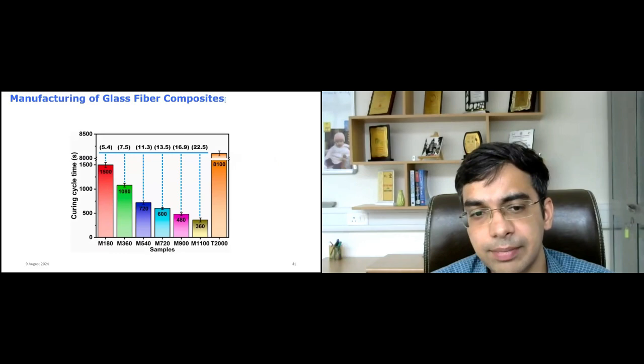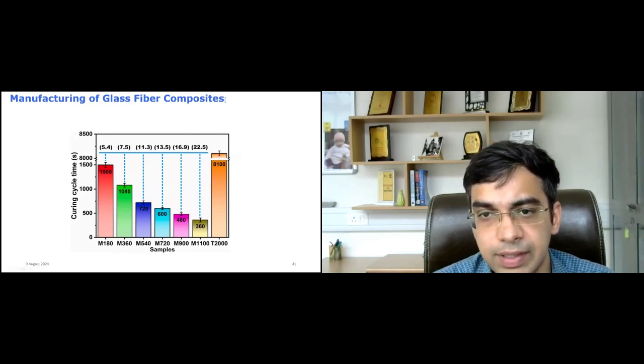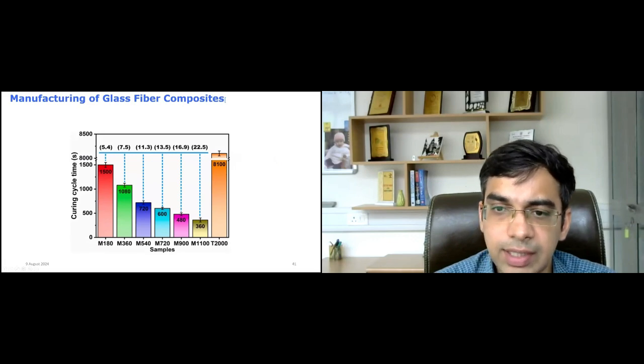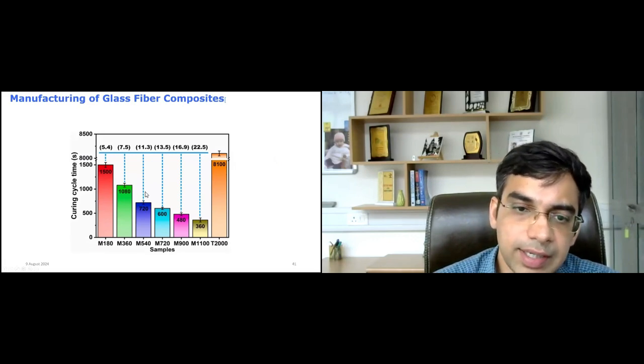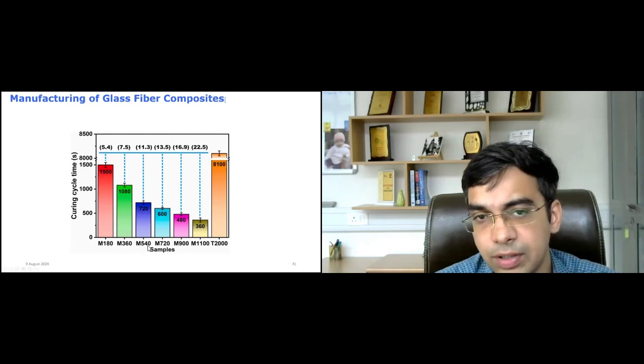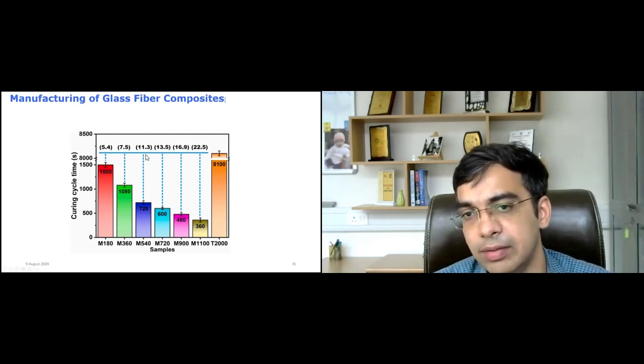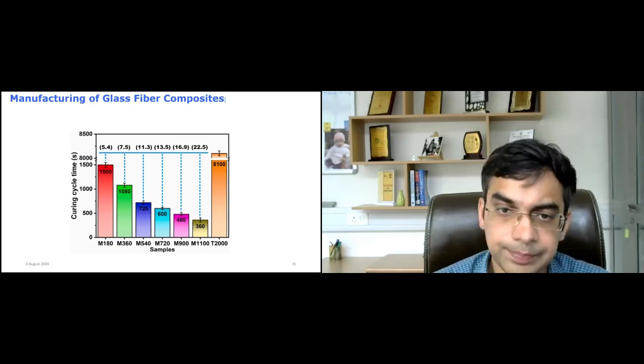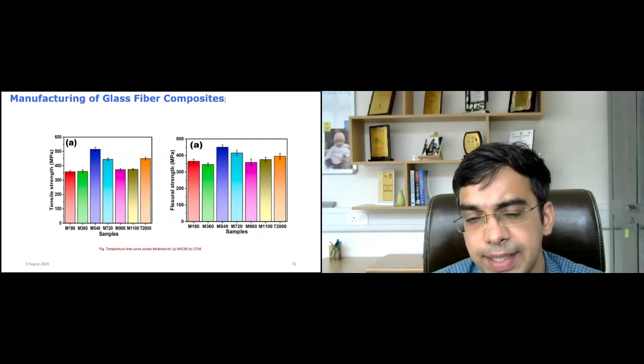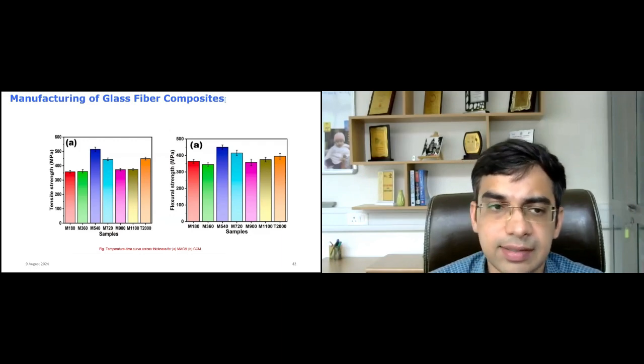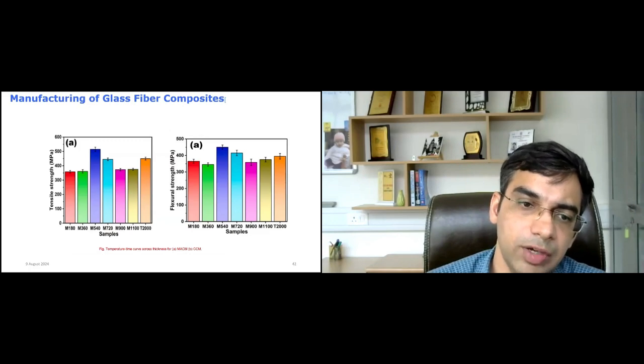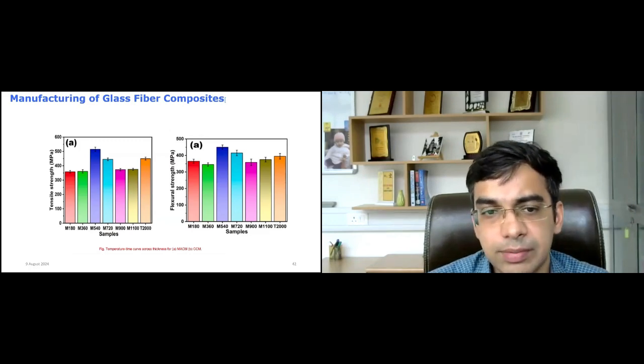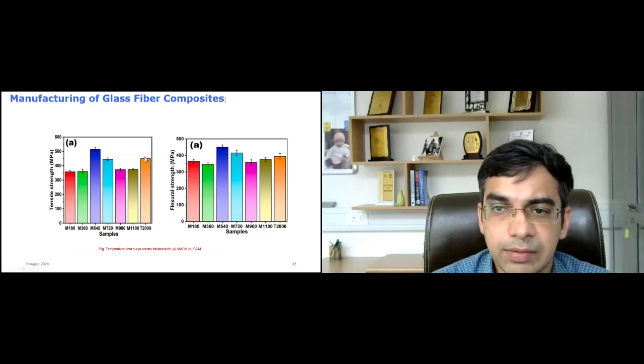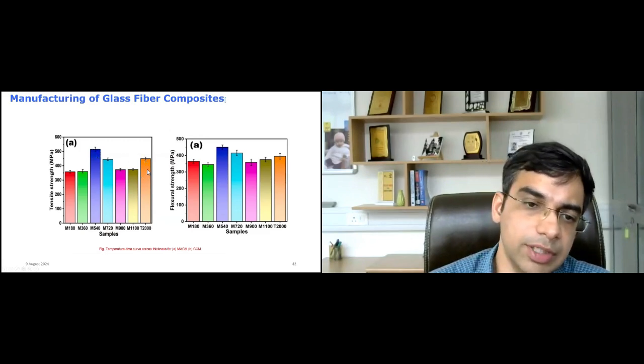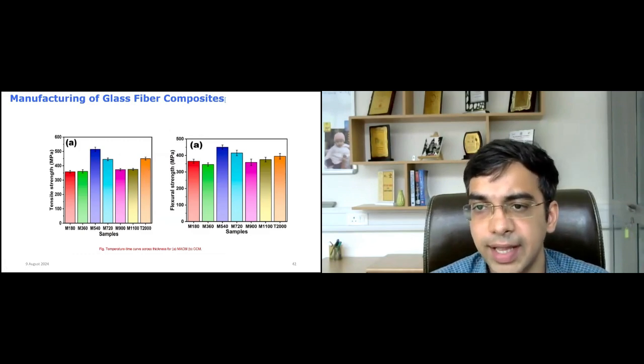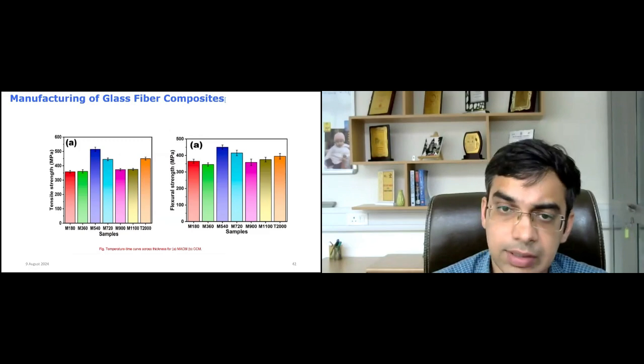So here is a comparison of the cycle time, and we can say that with respect to the thermal curing, that is T2000, at optimized power, say at 720 microwave exposure, 540 watt, it is almost 11 times less than what is observed with the thermal curing. We also investigated some of the mechanical properties of the developed composites in terms of ultimate tensile strength and flexural strength. And we observed that better tensile strength was observed at optimized microwave exposure of 540 watt, and it was significantly higher than what was even observed with thermal curing as a conventional manufacturing process. And similar trends were also observed in flexural strength testing.